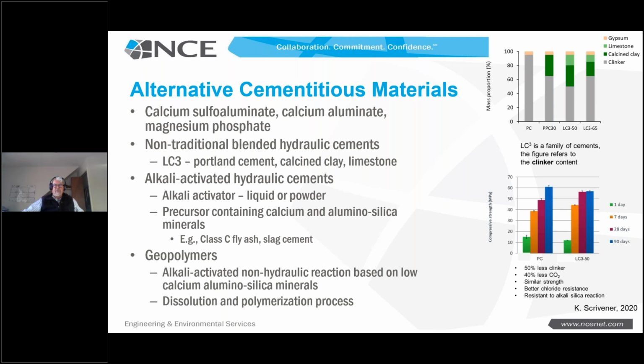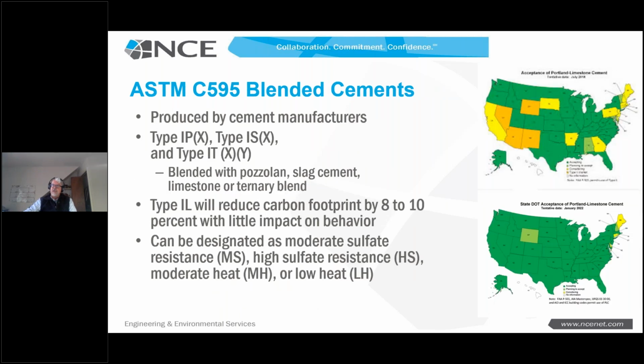A lot of individuals are very excited by alkali activated hydraulic cements that are still hydraulic, but have no clinker. You could take a low calcium fly ash, and a high calcium fly ash, class C, or a slag cement, and activate it with an alkali activator, and you'll get a hydraulic reaction that will form hydration products similar to Portland cement hydration. Another alternative is geopolymer,